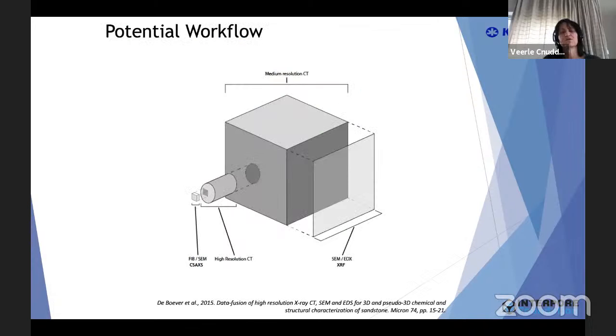So a typical workflow that is possible is, for instance, taking a bigger sample, scanning it at lower resolution, maybe having it polished so that you can combine it with EDX or XRF. Depending on the composition, you can take subsamples for higher resolution CT and even go to other techniques which are even higher in resolution in 3D, such as FIB-SEM or cSAXS, for instance.